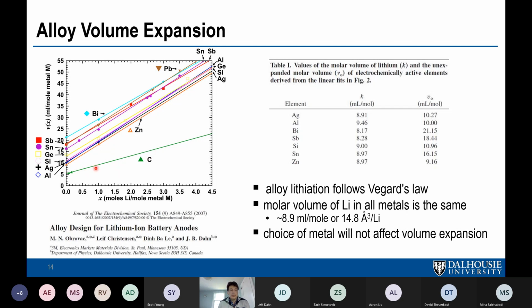And of course, carbon or graphite is different because it's intercalation. And so you have that mechanism where it's already an open structure and it doesn't need to expand as much as these materials, where they have to break bonds and lithium has to find its own place in the structure. And this represents the slope of that line, and you can see it's about 9 plus or minus a small amount for all these elements. So it really doesn't matter which element you choose, the volume expansion is going to be the same.